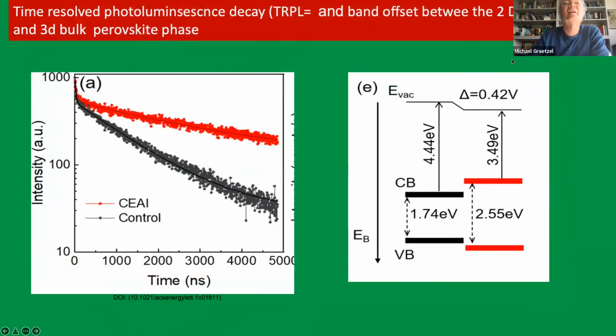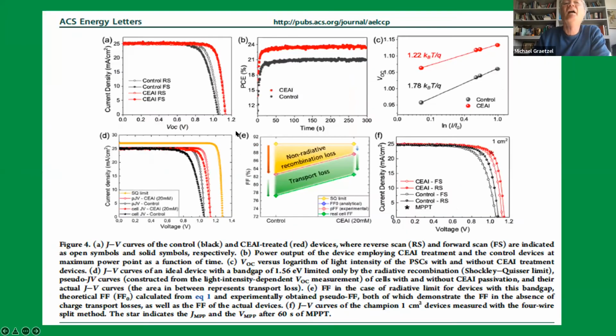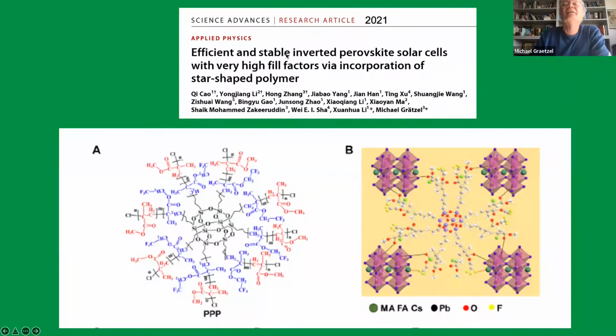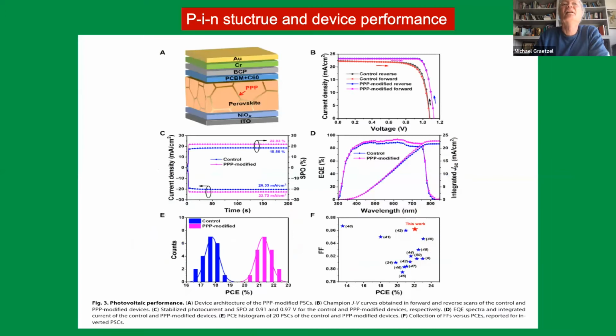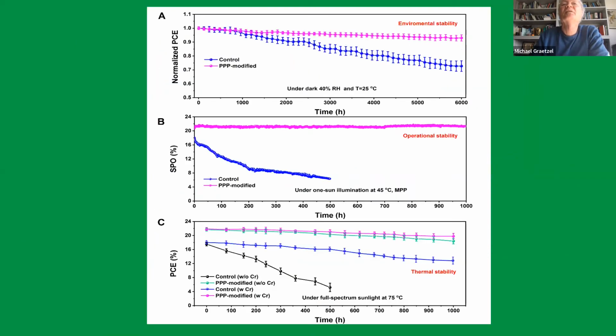And here we see again the recombination. This is photoluminescence decay. Slowed down, this means radiationless recombination is blocked by the mediator. And you get a higher voltage, you get better stability. And this is for another structure here where we use a PIN configuration. So there are many examples for this where with the right chemical design, you can really get highly stable systems. For example, this is here in the dark. So, I mean, it's just shelf life over 6,000 hours.